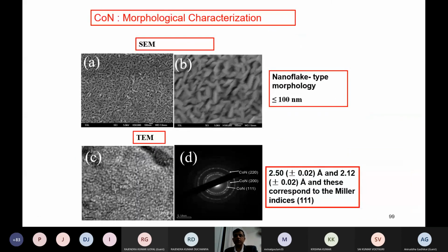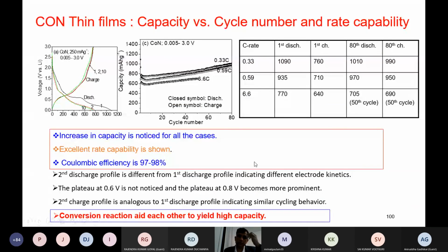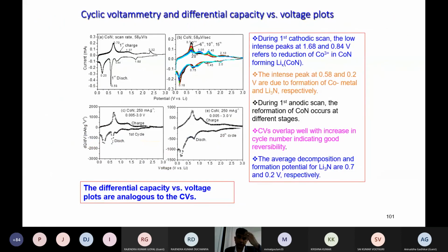So again, if you want to see whether there is a nanoflake or not, SEM and TEM will clearly tell the information about the d-spacing as well as the morphology of the sample. Again, reasonably almost like 1000 milliamps, reasonably good. Again, at the end, although these materials are very performing, we have to reduce the voltage for the real applications. This is my own concluding comment I'm suggesting for any young researcher who wants to continue this type of material: how to reduce the potential is a little bit of a question mark for this type of oxides.